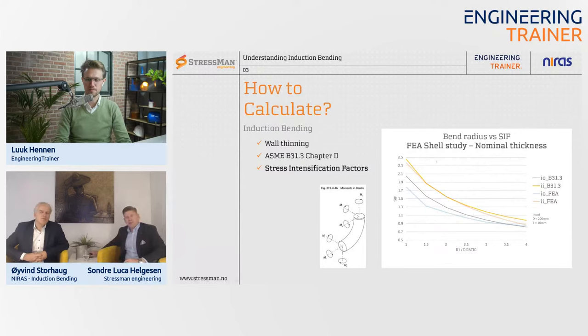But what is interesting here, this was based on a shell study, meaning that you have equal wall thickness all around the FEA model. And then we get approximately the same numbers up to three times the diameter in bending radius, and then it drops down. But what we can see, which is very nice, is that B31.3 is always giving a higher number or the same number as what we get from FEA.